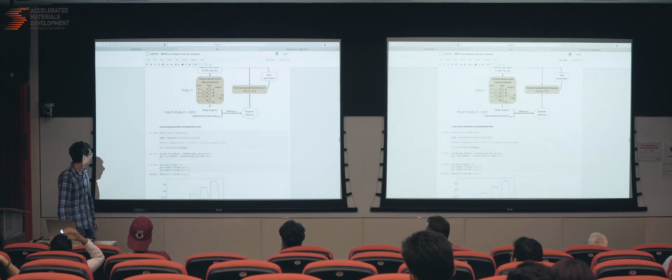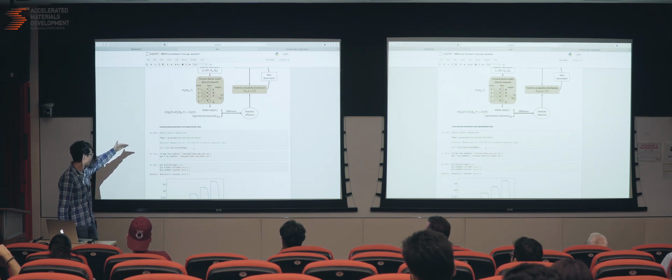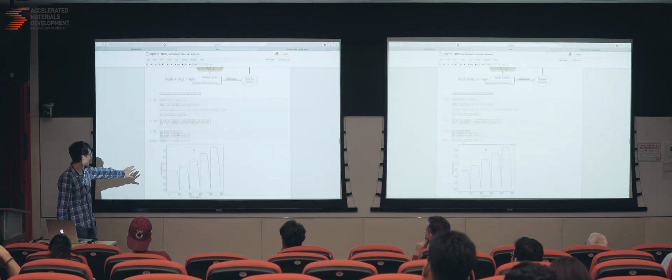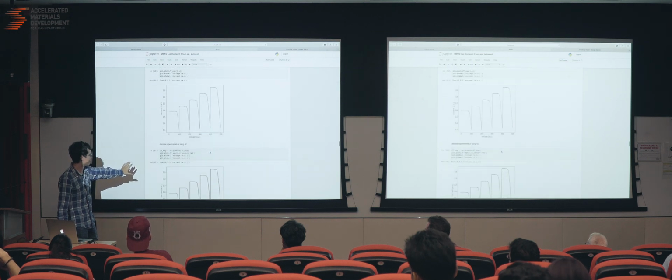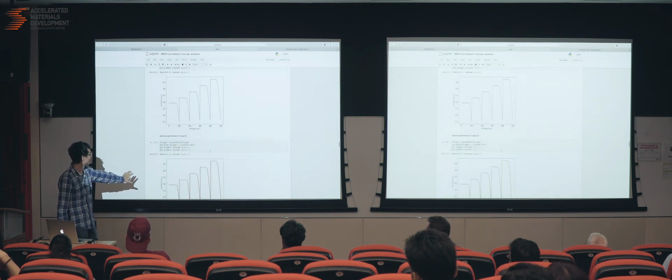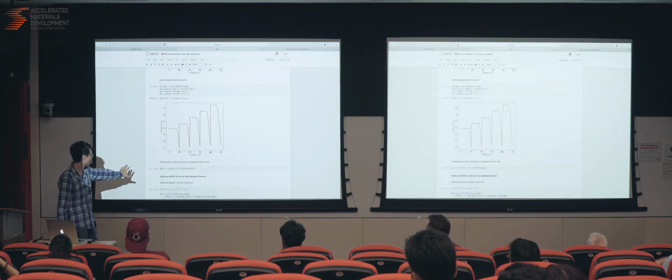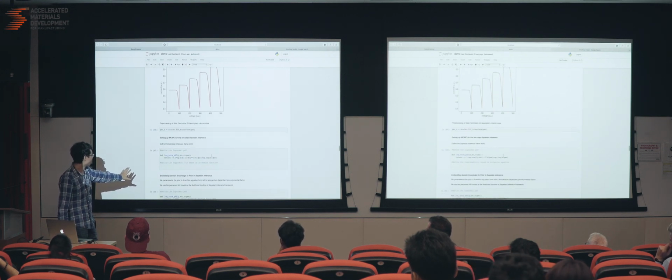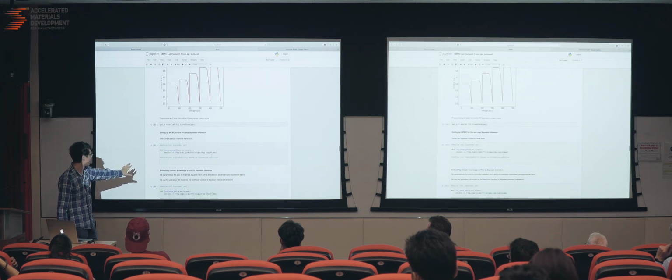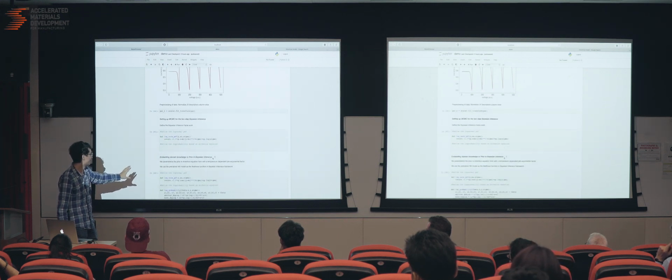All right, so now we could do the Bayesian inference. First of all, we can look at our experimental data with the experimental variation. In this case, we are varying the temperature in the MOCVD chamber. And these are the actual experimental curves, normalized. After that we feed this into a denoising autoencoder. So this is how it looks after you denoise that, and then you fit the whole thing into an MCMC framework, and here we define the prior.